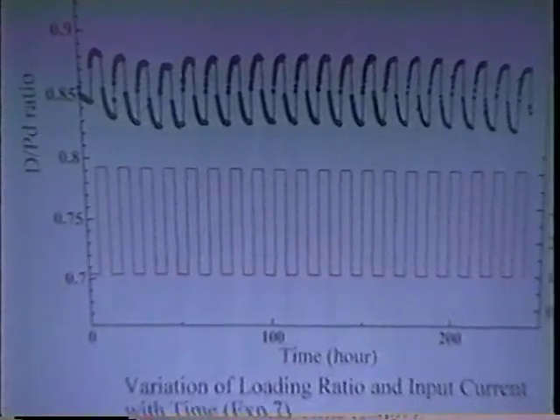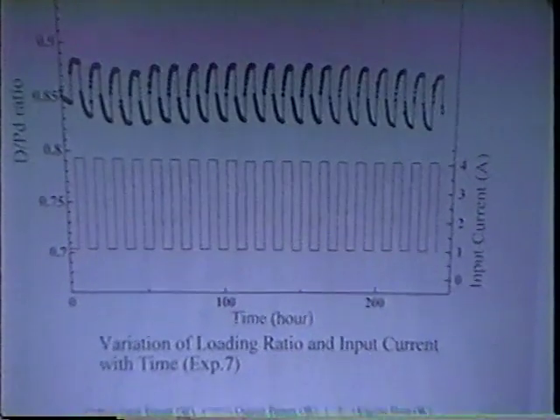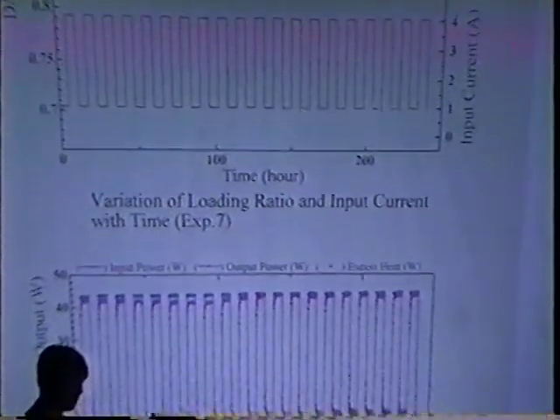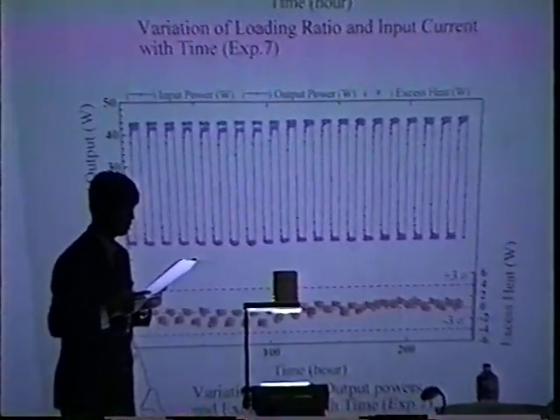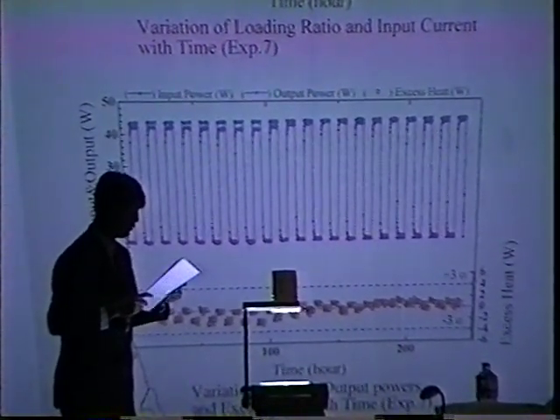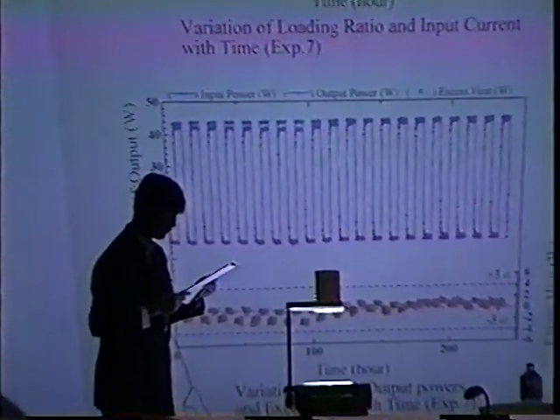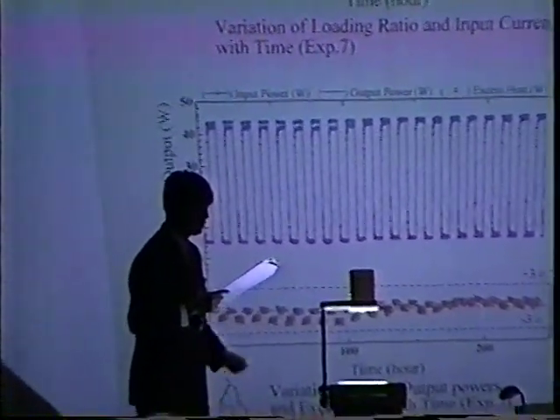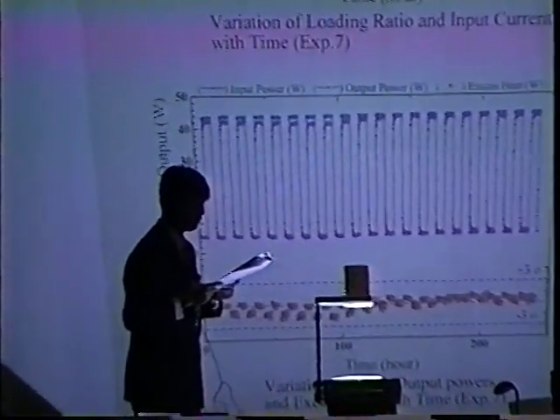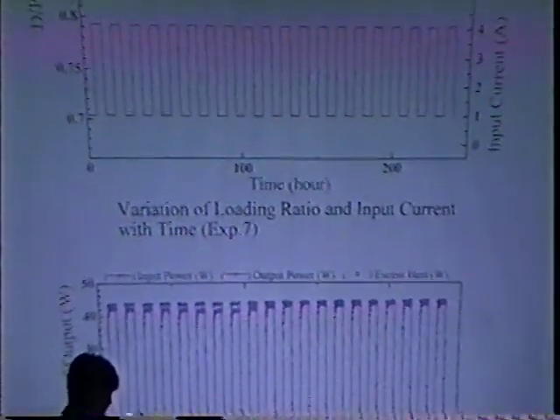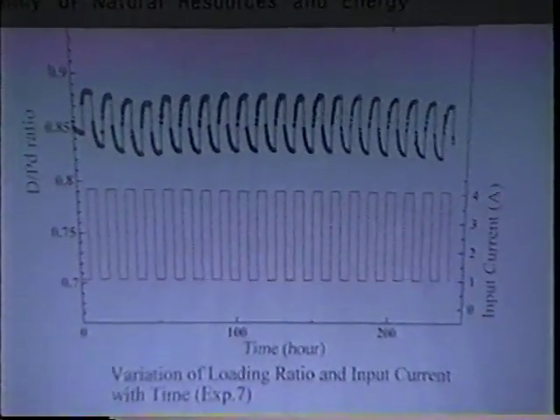For about a day, we stopped electrolysis and changed to the low 1 ampere, high 4 ampere mode, with 6 hours duration for each of the low or high modes, done for about 240 hours. Then the low-high mode electrolysis technique was fully used by the open system study group of our laboratory. Excess heat was observed, but not over the 3 sigma level. The loading ratio was higher than those of experimental 4 as a whole, but changed periodically on average from 0.82 to 0.87, corresponding to the current changes of the low-high mode.